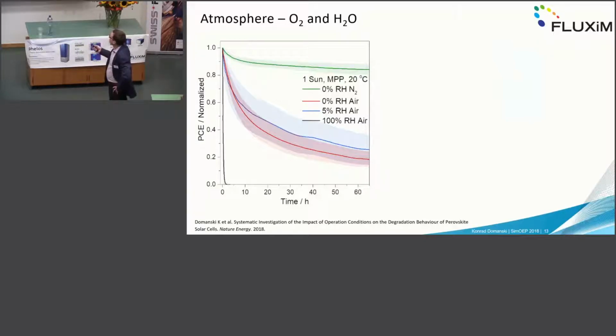And when we added oxygen to the chamber, you see that the device degraded catastrophically faster. And then we see that addition of a further 5% of water doesn't really change things so much. But when we added 100% relative humidity, the device dies immediately, within several hours.